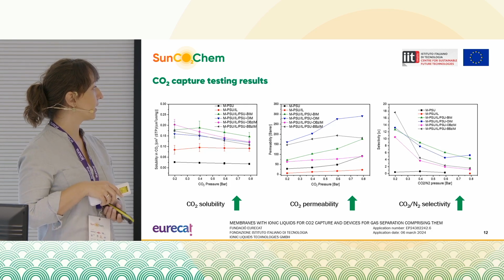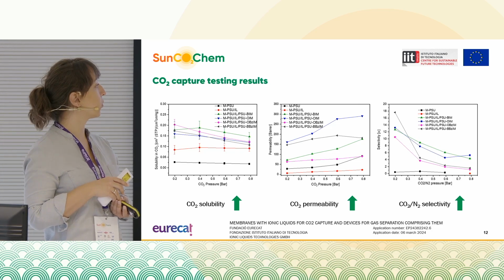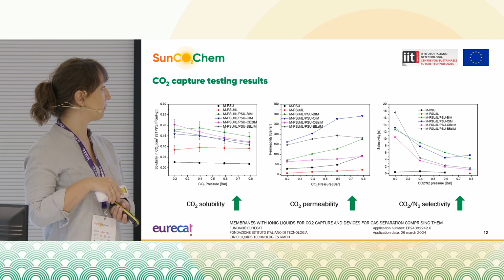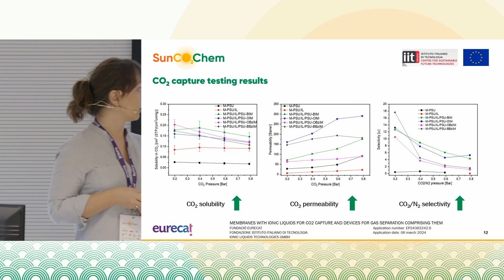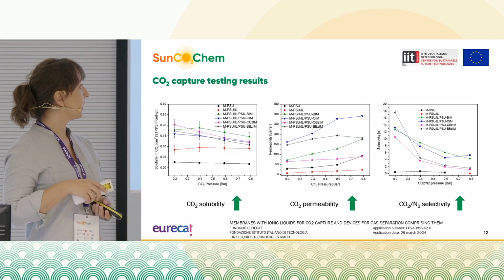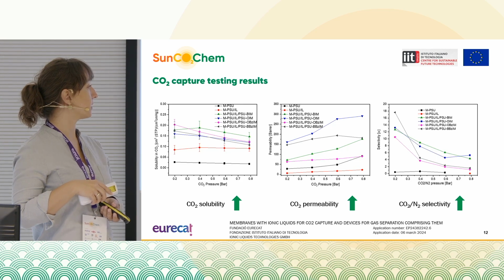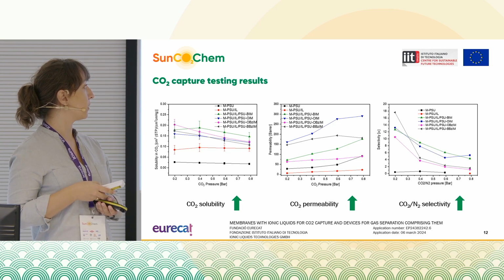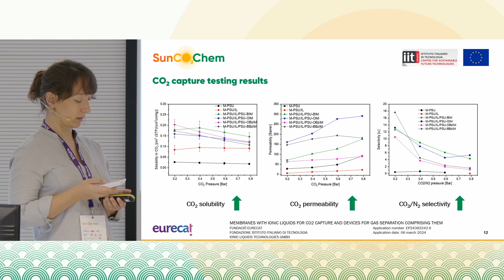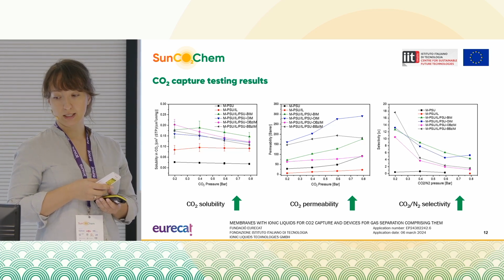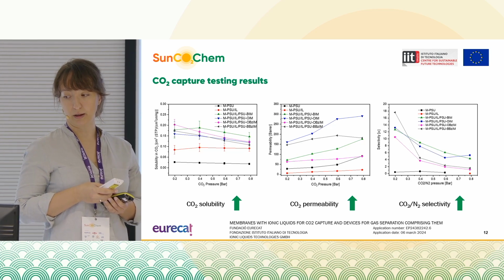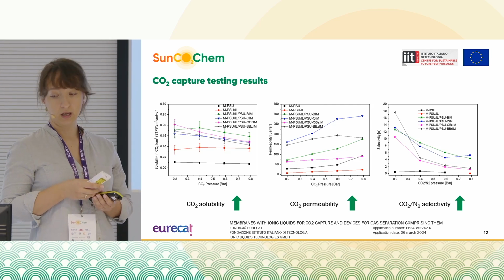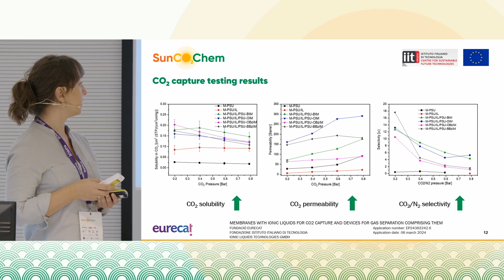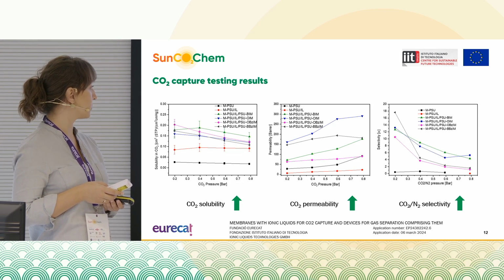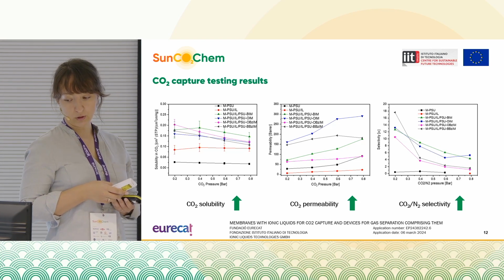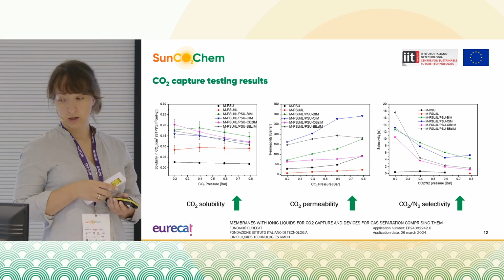The CO2 and nitrogen selectivity was calculated based on the permeability values for CO2 and nitrogen. And again, we saw the increased selectivity values for all the membranes that were containing modified polymers. With these results, we were able to apply for a European patent in between Eurecat, IIT, and IoLiTec on the membranes with ionic liquids for CO2 capture and devices for gas separation comprising them.